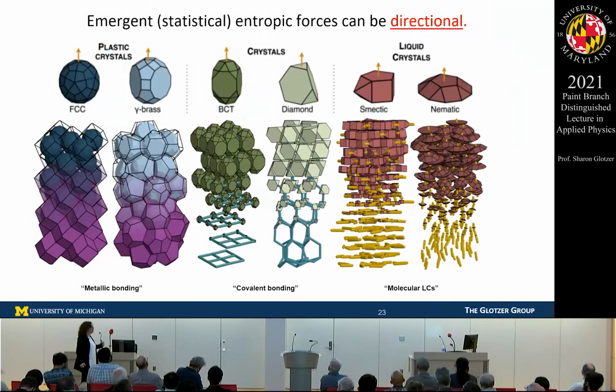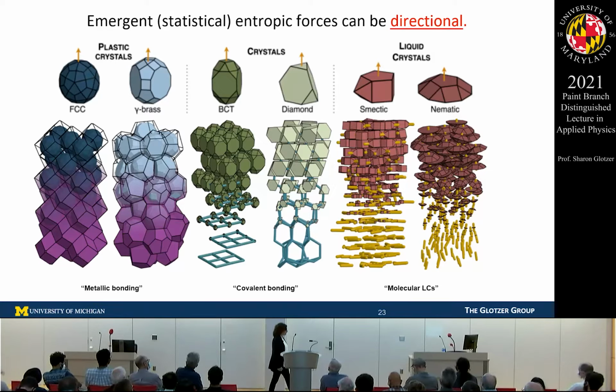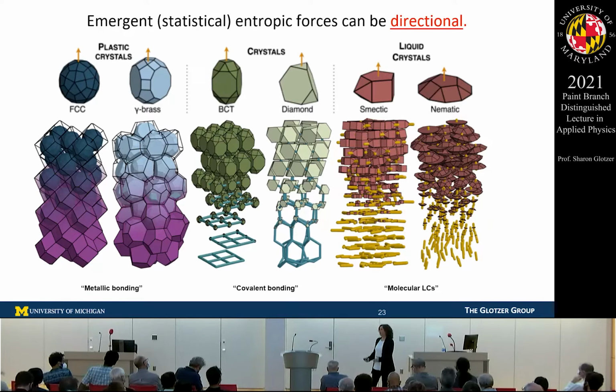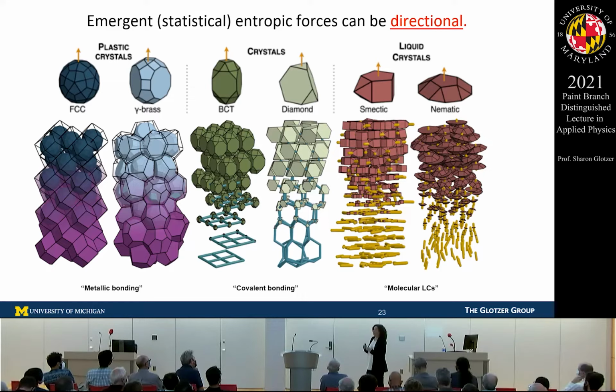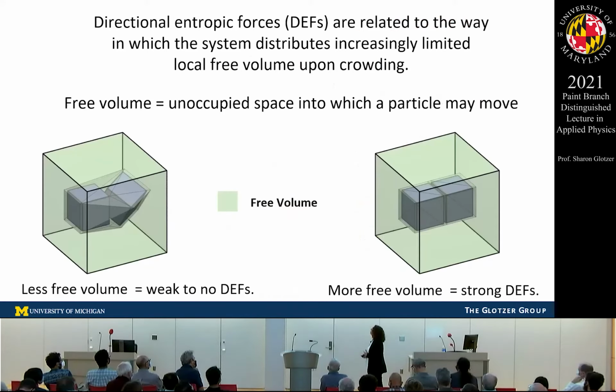The thing that we learn from all of these simulations that I showed you, that goes beyond what we maybe learned from Onsager or from the hard sphere simulations, is that, we know you can have statistical entropic forces. We've known that for a long time, and they come up in all kinds of different situations. What we understand now is that these emergent statistical entropic forces can be directional. And that directionality can produce a valence that gives you these different crystal structures. And these directional entropic forces are related to the way in which the system distributes local free volume in the system.